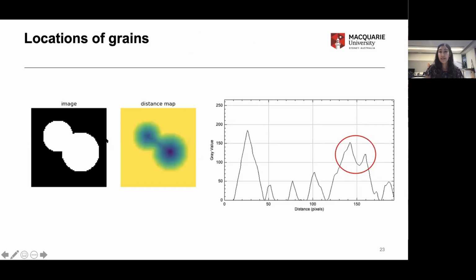This image shows that a little bit clearer. So the center of two grains, and then the distance between them is at this minimum distance where we need to cut. And this is exactly where we will define these saddles in our grayscale intensities.